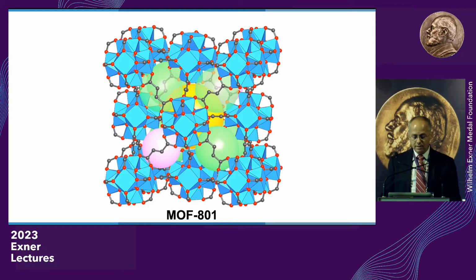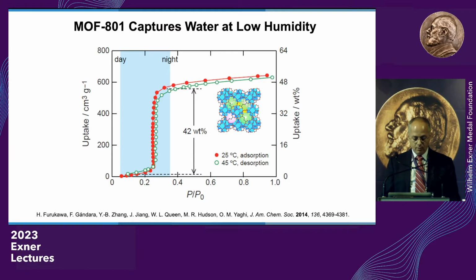So this is the first MOF where we discovered this, and the students came in with this kind of isotherm where the water uptake in the material is shown in red. And immediately I looked at this and I thought, oh my God, this material takes up water at around 20% relative humidity.